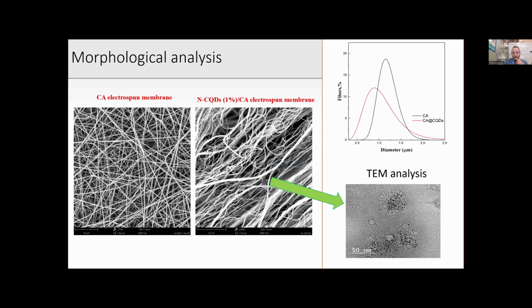Here you can see the morphological analysis of the pristine cellulose acetate electrospun membrane before and after the introduction of nitrogen carbon quantum dots. You can observe a more disordered structure, which can be ascribed to the presence of the aromatic groups of nitrogen carbon quantum dots, which can lead to an increase in conductivity and instability of the Taylor's cone in the electrospinning process. So this can justify the disordered structure, the reduction in fiber diameter, and the increase in specific surface roughness.